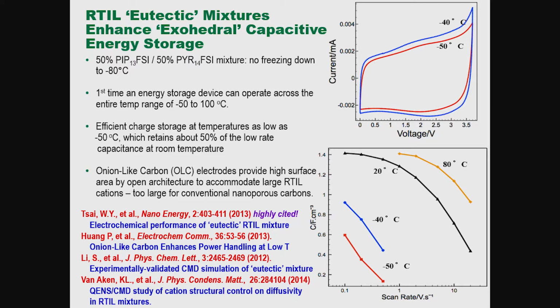No freezing down to minus 80 centigrade. We were able to show that an ionic liquid onion-like carbon electrode functions very well with these large cations, allowing capacitive performance, very nice power and energy output, even down to minus 50 degrees centigrade and up to 80 degrees centigrade. So this is Siberia and the Mojave Desert, I guess, is the range we're interested in.